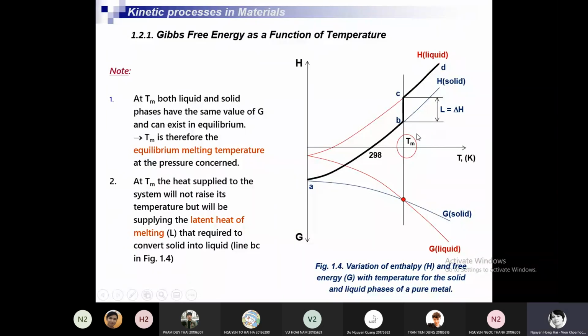And at this temperature, if we continue to supply heat, the temperature of the solid does not increase, but it converts from the solid state to the liquid state. So this heat is the latent heat of melting, equal to the difference in enthalpy between liquid and solid. After transformation from solid to liquid, from point C, if we continue to supply heat, the enthalpy of the system, now liquid, will increase by interval CD. So this is the enthalpy curve of the system with the transformation from one state to another.